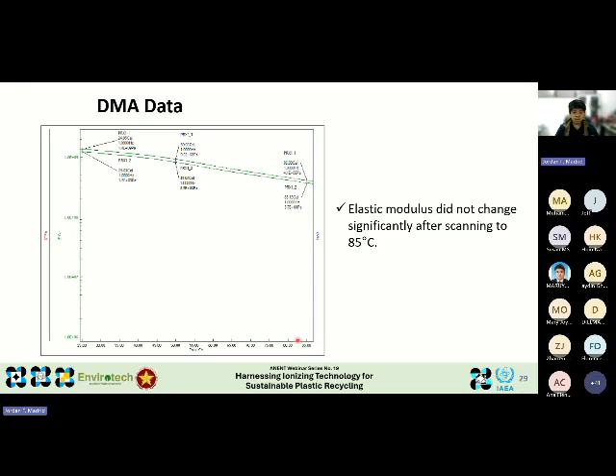The results were very promising. The elastic modulus, which tells us the material's ability to resist deformation, did not drop drastically when the temperature was raised to 85 degrees Celsius. To put this into context, 85 degrees Celsius is well above the range of typical outdoor temperatures in our environment. God forbid that we will reach that temperature in the future due to climate change.